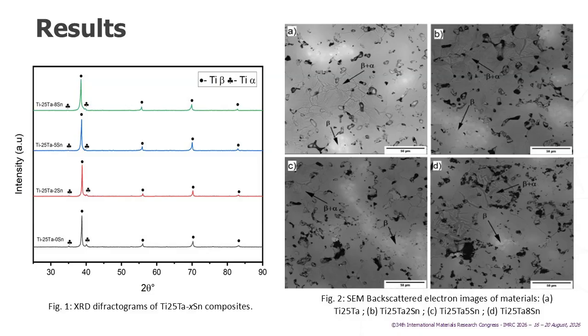The mechanism of this transformation is based on the nucleation of the alpha phase at the grain boundaries of the beta phase and its laminar growth inward, dropping the beta phase during the slow cooling process from temperatures above the transformation temperature of 882 degrees. Figures B, C, and D show microstructures similar to those observed for the titanium 25 tantalum alloy.